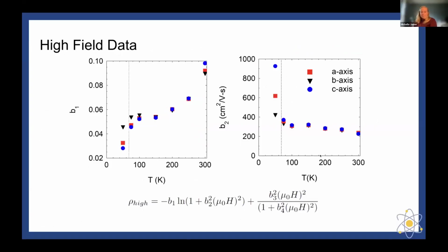So for the high field data, whenever we're taking a look at mu, B1 and B2, this is also related to mobilities, and they're also in centimeters squared per volt seconds. As we can see here, especially for the mobility that's related to a similar term in the slide prior, the B squared, we have something that is extremely large. So we see that the mobility levels out at around 300 centimeters squared per volt seconds, even in the antiferromagnetic state. So we notice that the mobility doesn't really drop down as we increase temperature, which is a little bit unique for a material.